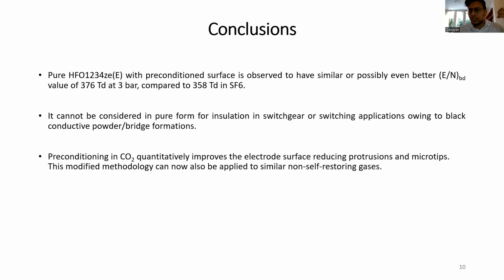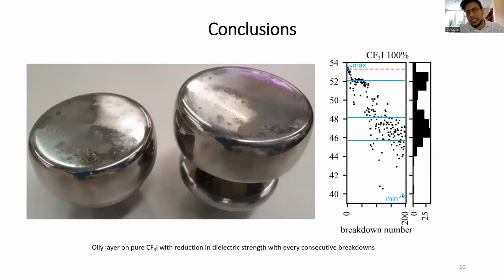Also, if you recall, I spoke also about CF3I. So I'll not go into the complete details about it, but CF3I is also such an ugly gas, because here you don't have much carbonization, but it really forms like an oily layer on the electrode, as you can see over here. And that basically reacts with the electrode surface as well. Even for this one, you see with each consecutive breakdown, there's a reduction in the strength. So you start off with 54 and you end somewhere in 40. There's a paper which basically does the shots and says the mean value at this pressure is 40. But then it really doesn't make sense because you can't take a mean for these gases, like for the non-restoring gases.